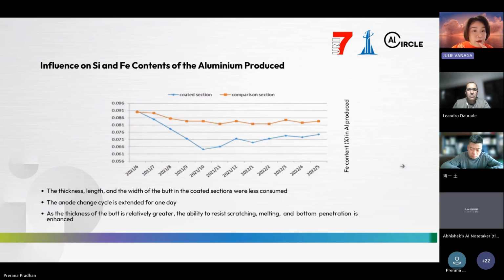So, the influence on silicon and iron. Well, because this will directly influence the quality of aluminum. The product quality is the lifeblood of the aluminum producer, and our coating also brings tangible improvement to the quality of the final aluminum product, specifically by reducing the silicon and iron impurity contents.